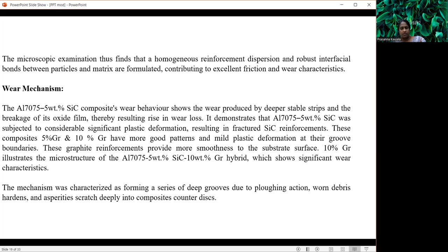Because it is undergoing plastic deformation, once we add the graphite, which gives a lubricating effect, here it has better patterns with mild plastic deformation at the groove boundaries. So these graphite reinforcements provide more smoothness to the substrate surface. Whereas with 10% graphite, the microstructure shows significant wear characteristics. Graphite particles disperse throughout the aluminum matrix, which helps to reduce the mean size of the wear particles.